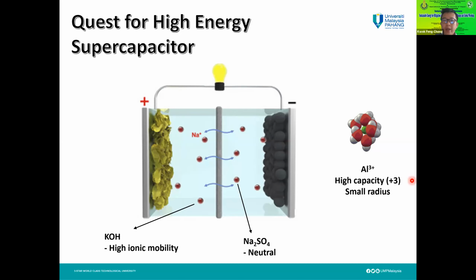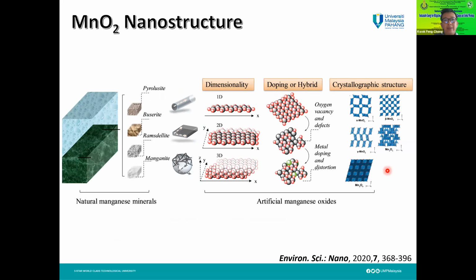So I threw them a challenge to see whether we are able to develop a material. That's why I call it a quest: to develop a material that can accommodate this ion. Theoretically, it's proven that it has a very high charge capacity, but can we prove it experimentally? We need to find a material that can accommodate this aluminum ion. So we started out with the manganese oxide nanostructure. As you know, manganese oxide can be found abundantly in nature, where it can exist in different phases: pyrolusite, ramsdellite, and manganite on the left-hand side. At the same time, I'm a materials chemist, so we can synthesize manganese oxide in the lab in different dimensionalities. We can synthesize it as nanoparticles, as 2D sheets, and as 3D bulk material.